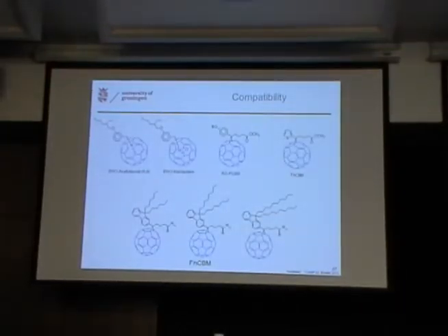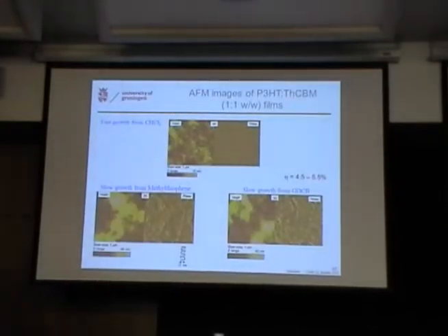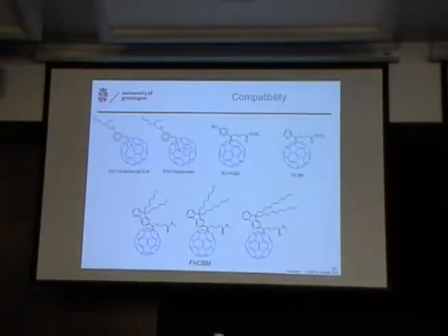And you can play with the compatibility, of course. You can play with the compatibility with respect to electronics. This one is a slightly stronger acceptor. This is a very strong acceptor. You can put side groups on the PCBM. This one was specially made for polythiophene, thinking that this thiophene has some similarity. And the ones on the bottom were made for polymers that have these side groups. You have the polymers that have the dialkyl fluorene moieties in the polymer. You have them with C6, C8, and C10 tails. So we made these fullerene derivatives so that they can mix with the different polymers.